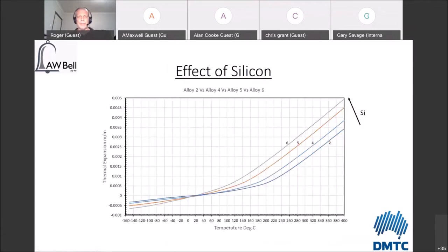Then the effect of silicon. Now, you can see that as we add silicon here, we still have an Invar effect going on down at low temperature, but as you go up in silicon content, you're getting less and less effect of this low thermal expansion down here. Alloy 2 was the one that was shown on the previous chart, and you can see that as we go from the lowest silicon contents up to the highest, it doesn't work for us at all.